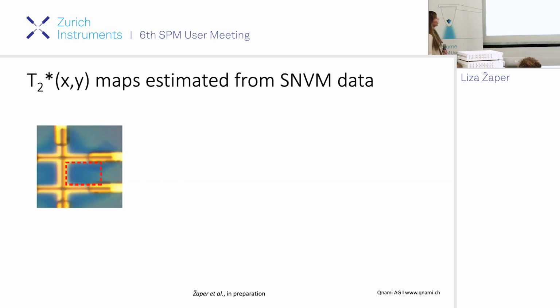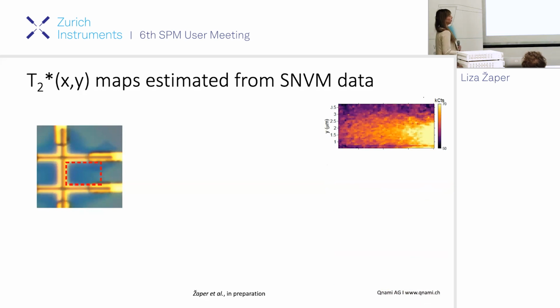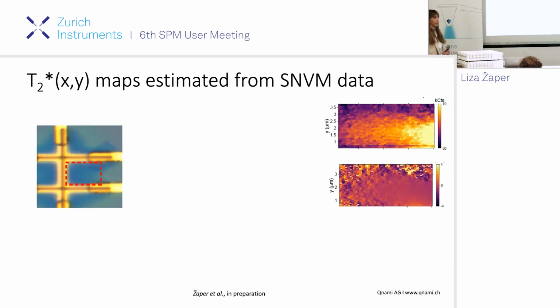Even more, if you take a look at the optical micrograph, this is visible as a difference in the material color. And if you have a look now at the fluorescence scan that we made, you see that if we go near to the nanowire, we have a reduction of the fluorescence. The reduction of the fluorescence can occur due to several different effects. First is the material contrast. The second is topological structure that impacts also the scattering of the electrons. And the third is quenching, so the direction of the magnetic field with respect to the quantization axis. At this point, it's very hard to say what is the cause of the fluorescence decreasing.